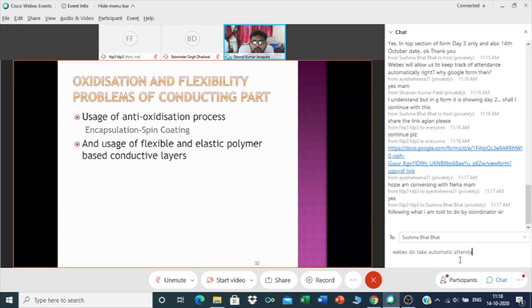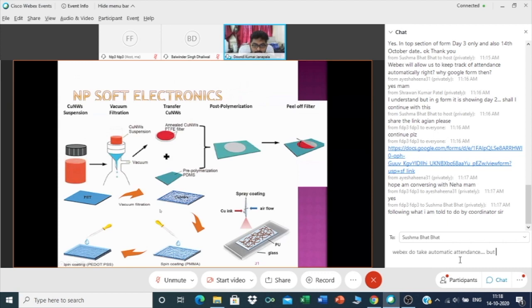So in order to increase its durability, what we will do is, after coating the nanoparticle, we will put the sample on top of the spin coater, put a drop of polymer, mixed polymer, and use the spin coater at maximum speed.